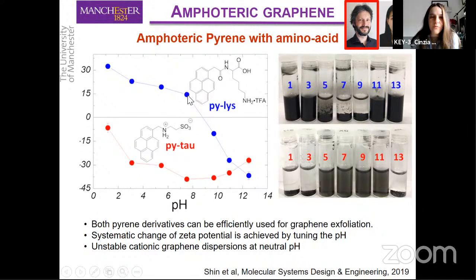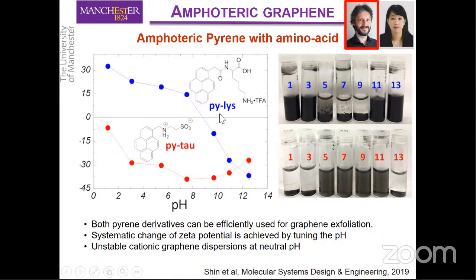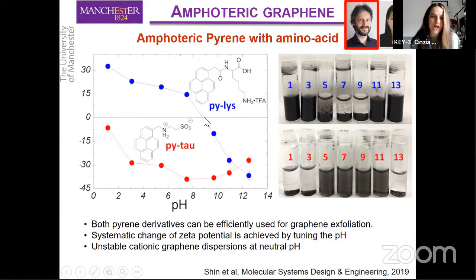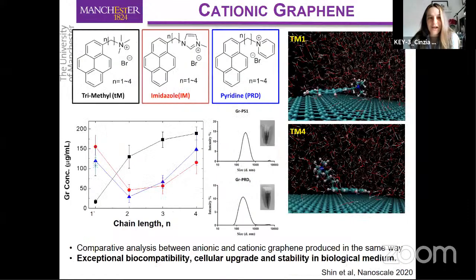In the case of the pyrene functionalized with lysine, we have been able to cross the charge neutrality point and produce both positively and negatively charged dispersions. However, those were achieved at very high pH, which is not suitable for biomedical applications. And so I'm about to finish. We decided, therefore, to use cationic pyrene derivatives.